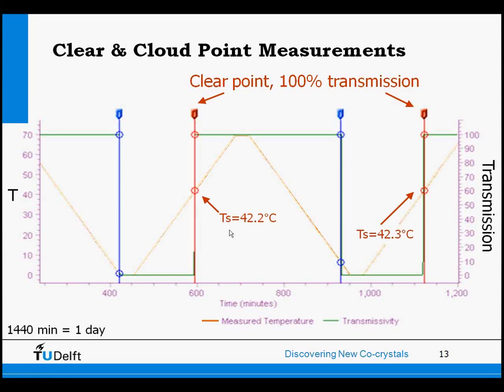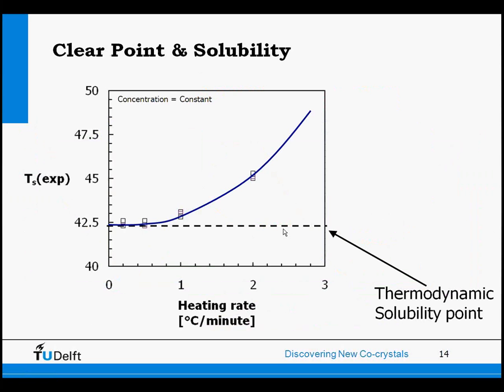And if you do that multiple times, you see that the saturation temperature hardly changes. So that enables you to get solubility data within 1 day. And well, you have to use a specific heating rate. So we investigated how the heating rate influences the saturation temperature. For one specific composition, we measured the saturation temperature multiple times with a specific heating rate. And you see that the lower the heating rate, the lower the saturation temperature.